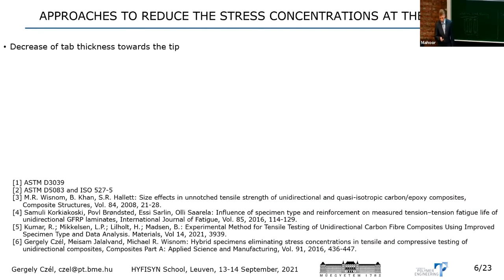So what can we do with this? Because the test is so simple. We just need to transfer the stress, the normal stress, to the specimen, and then watch at which force or displacement or strain or stress it fails. But we fail to do this right at the beginning, because we cannot transfer this normal stress to the specimen properly, because it's not uniform. So there are high peaks towards the ends of the specimens in the arising stresses. So what we can do is to try to reduce or eliminate these effects.